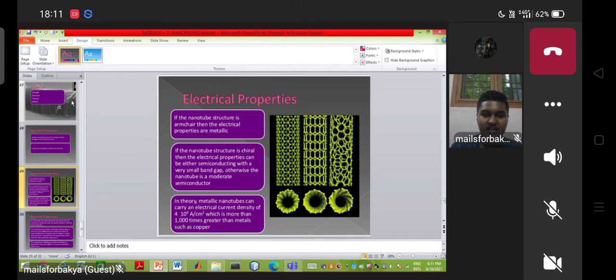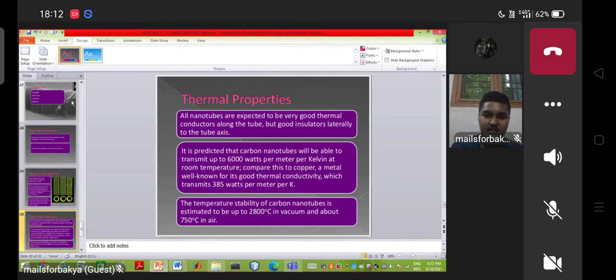In theory, metallic nanotubes can carry an electrical current density of 4 times 10 power 9 ampere per centimeter square, which is more than 1000 times greater than metals such as copper. Well, next, thermal properties. All nanotubes are expected to be very good thermal conductors along the tube, but good insulators laterally to the tube axis. It is predicted that carbon nanotubes will be able to transmit up to 6000 watts per meter per Kelvin at room temperature. Compared to this, copper, a metal well known for its good thermal conductivity, transmits 385 watts per meter per K. The temperature stability of carbon nanotubes is estimated to be 2800 degrees Celsius in vacuum and about 750 degrees Celsius in air.